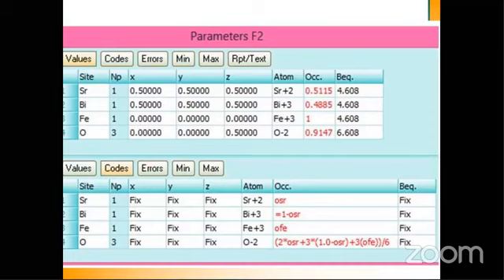It has to be reproducibly the same result when you finish the refinement. And oxygen vacancies were also generated, as you can see, 0.91. If it had not been replaced or doped, then it should be 1. Like iron, this particular position of iron was not doped. Only this particular position of strontium and bismuth were replaced with each other. These are the codes to do the refinements, and these are the final results.